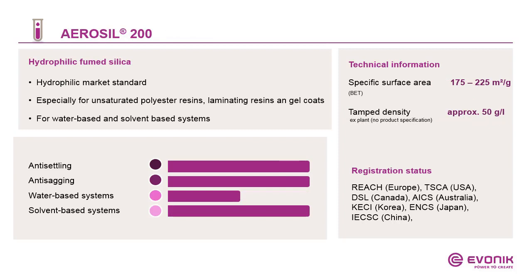On the Aerosil products, we have Aerosil 200, a hydrophilic fumed silica and the hydrophilic market standard, especially used for unsaturated polyester resins, laminating resins, or gel coats. It can be applied in water-based and solvent-based systems and provides a specific surface area of around 200 square meters per gram.